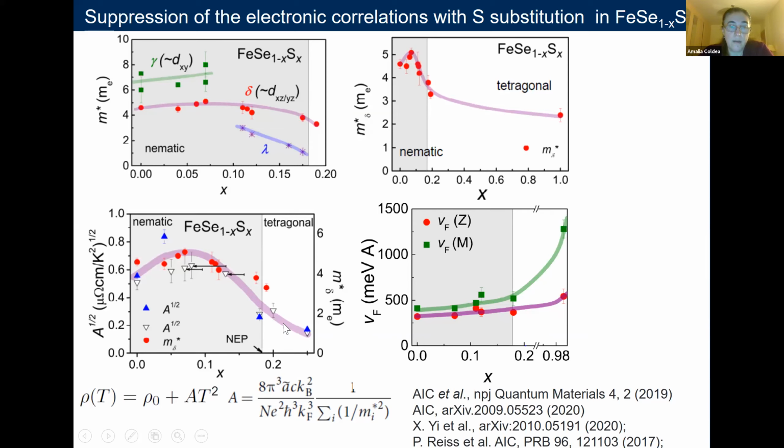And we compare these effective masses with the values of the A parameter measured by us and by Nagel's group. The A parameter is on the left side, and the effective mass is on the right side. Once we account for the nominal composition effects that Nagel used in his paper and shift all these points to the left, then we can see that all the data nicely follow a smooth variation, a slight increase towards 10%, and then a decrease as we cross these boundaries.